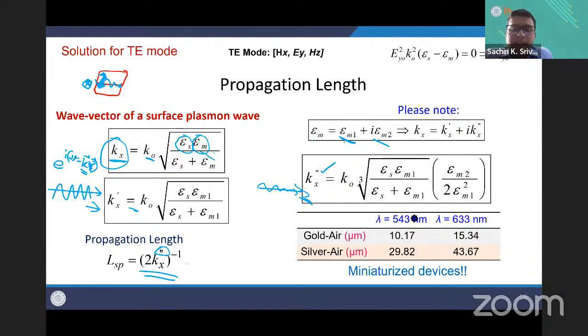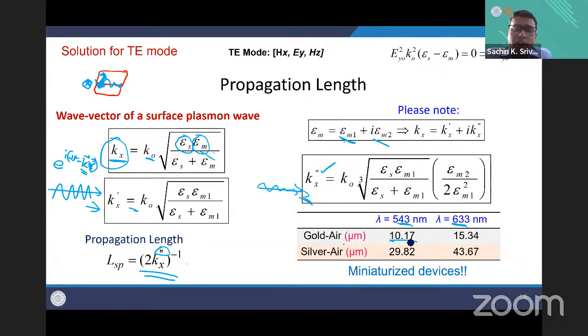And you can see that for gold, I have simulated this at two different wavelengths. I have calculated for the gold-air interface, the wave will go up to 10 micrometers and then die out, or 15 micrometers and then die out. For the silver-air interface, because the losses are small for silver, it can go up to 50 microns. You can make a device of 50 micron length, and that is perfectly fine. Such a small device you can make. You can make miniature devices.